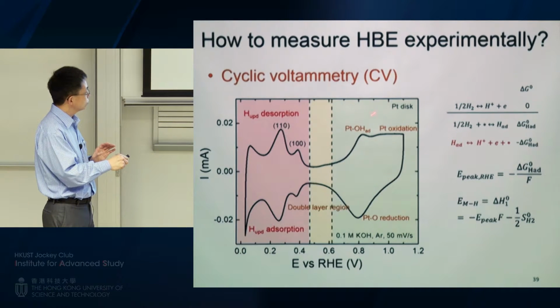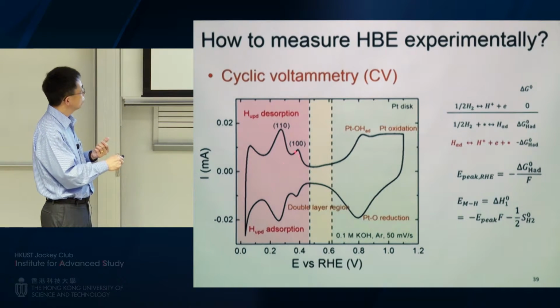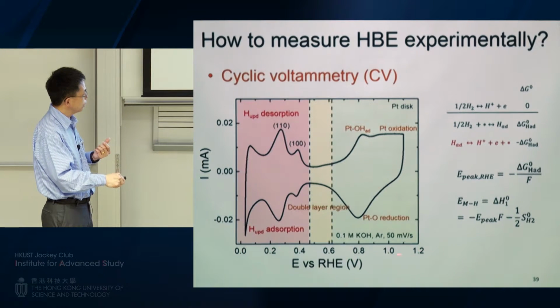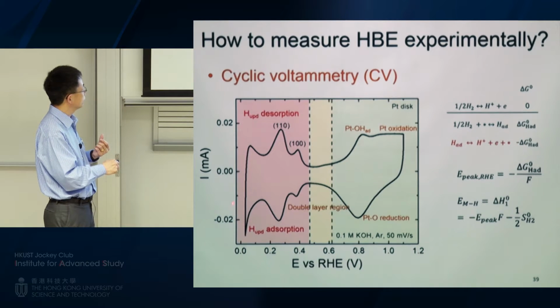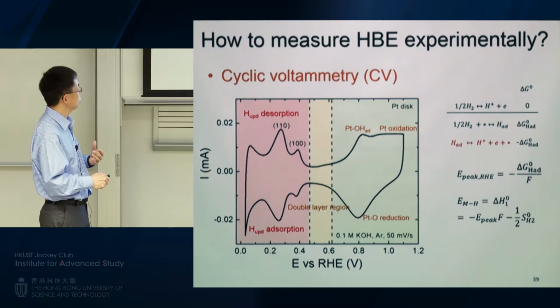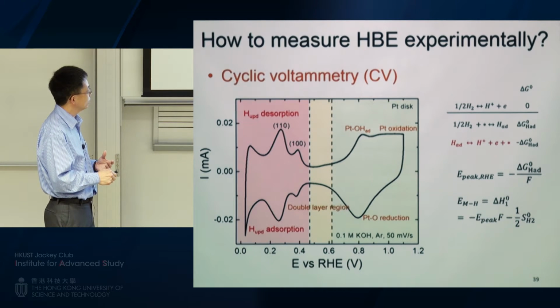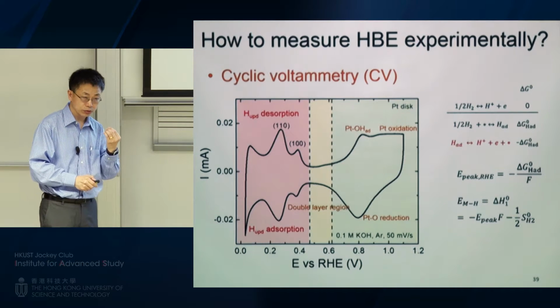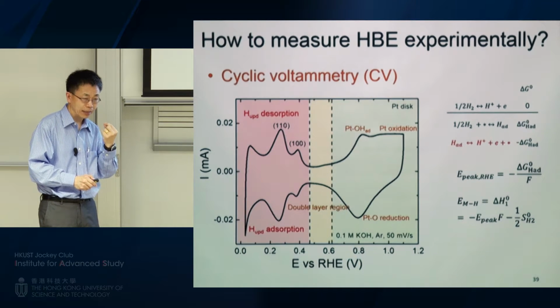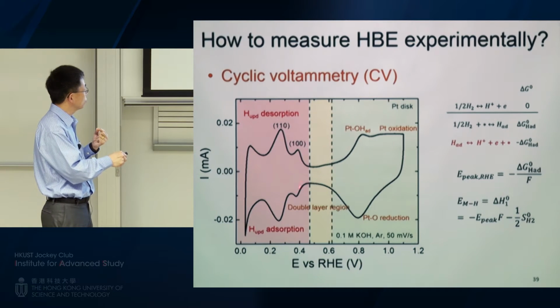This is the cyclic voltammetry plot for platinum. The horizontal axis is the potential, the vertical axis is the current out of the disk electrode. And I don't know how much you know, this is a very standard electrochemistry technique. So imagine if you scan the potential, at a certain point you oxidize platinum, and you take it back, and you reduce the platinum back. And then at certain potential, you're going to have this underpotential hydrogen deposition, meaning you're reducing proton into an atom, and that atom gets onto the surface of platinum, and you form a monolayer.